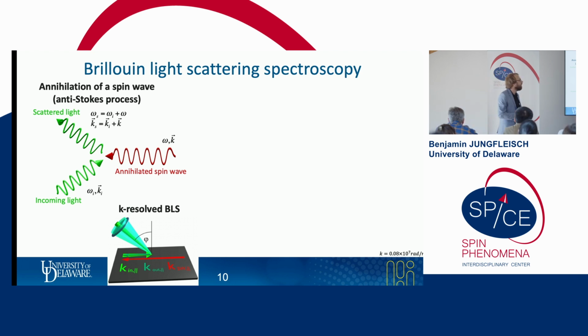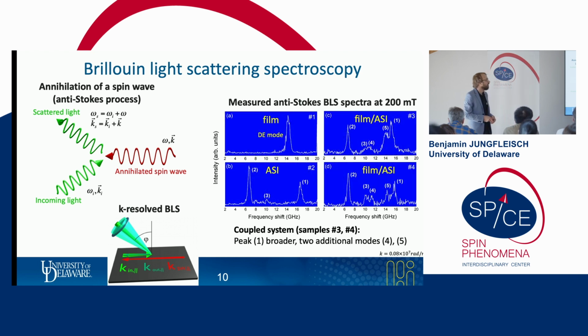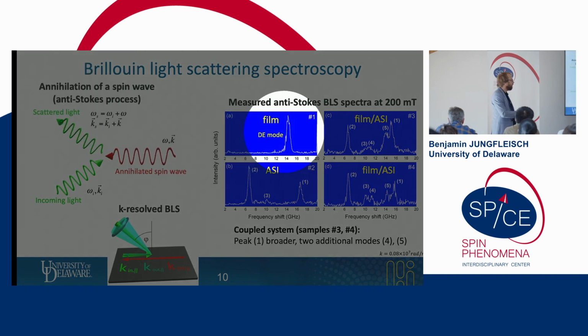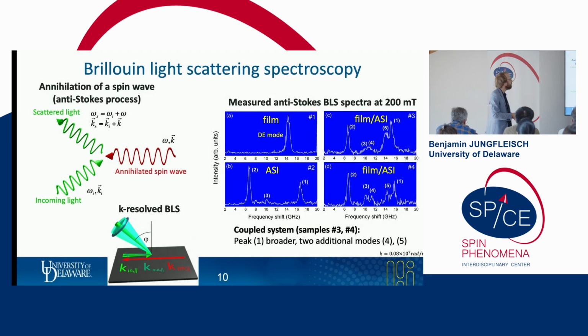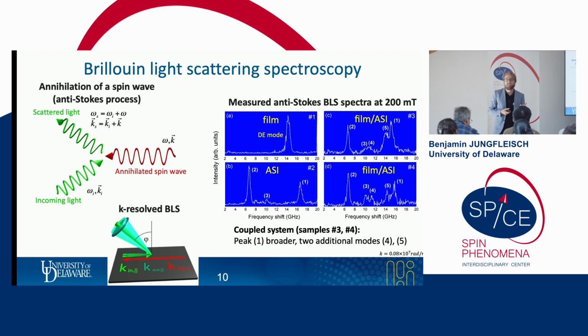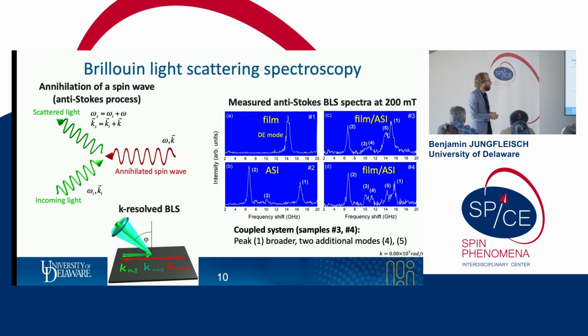So let's take a look at the raw data. So this is the measured anti-Stokes peak at 200 millitesla. On the left, we see the two control samples, film and isolated artificial spin ice. For the film, we only see one mode. This is the Damon-Eshbach mode. On the bottom, we see the corresponding artificial spin ice. It has 3 characteristic peaks, and I will explain them in just a moment. On the right side, we see the coupled system. So this is the film artificial spin ice system with 2 nanometer spacer layer and 10 nanometer spacer layer on the bottom. So by just looking at this, we clearly see that the coupled system has 2 additional modes, labeled here 4 and 5, and peak 1 gets broader.